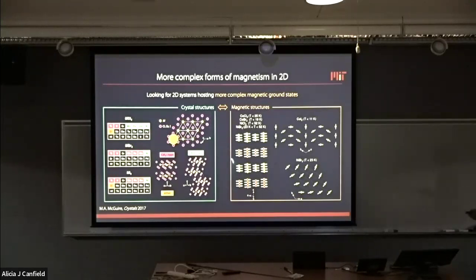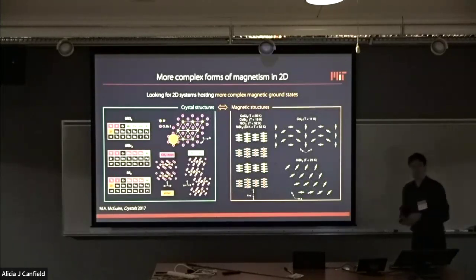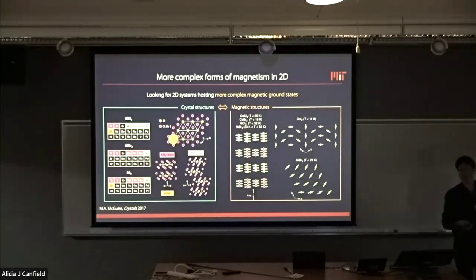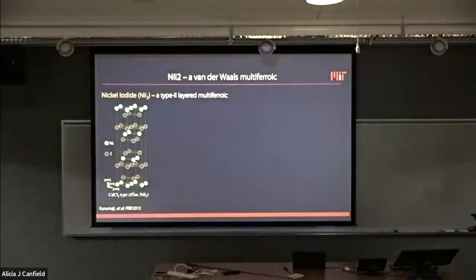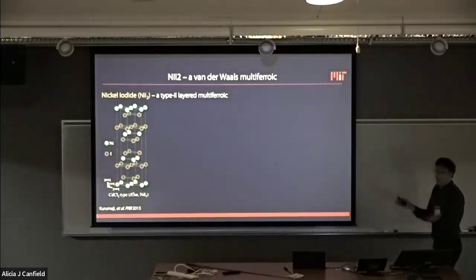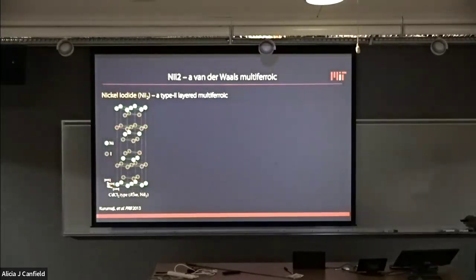There's two different types of structures. But most interestingly is that there's quite a variety and diversity of magnetic ground states. So you have some collinear ground states, typically antiferromagnetic collinear, but you can have some cycloidal states, helical states, etc. So the material that we worked on in the very beginning, and it turned out to be one of the most exciting ones that we've worked on since, is nickel iodide, which is a type 2 layered multiferroic.